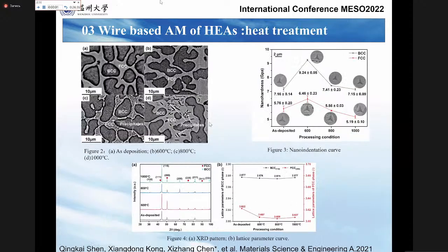For the microstructure, I think it's simple, not so complex. It's mainly BCC, FCC, plus some precipitations. We also did the heat treatment, like A, B, C at different temperatures. Okay, for time limit I will introduce shortly. So the precipitation will change with the heat treatment temperature.